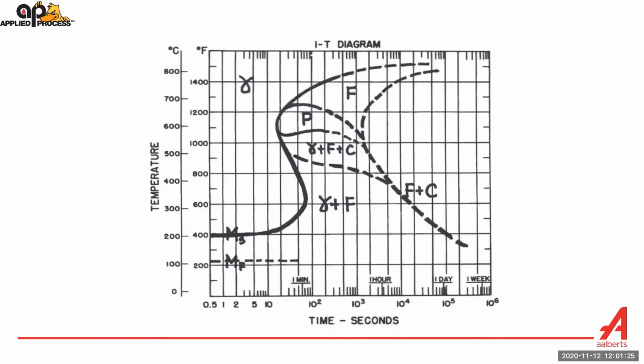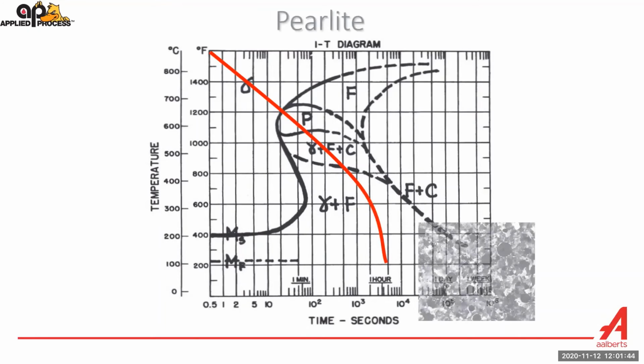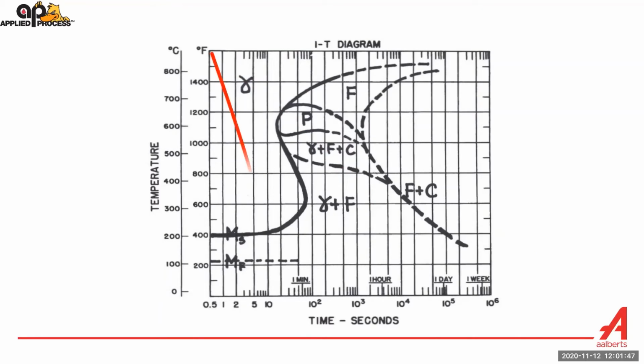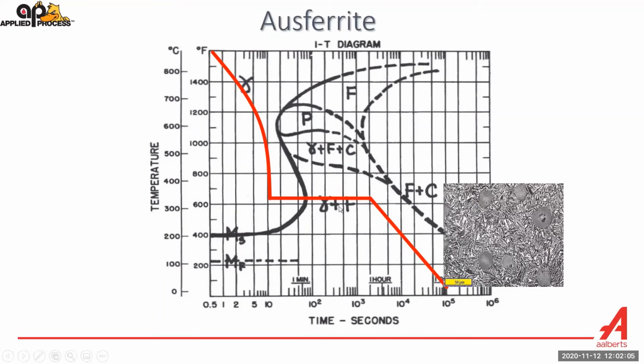So again, we go back to the IT diagram or the TTT diagram. This one is for ductile iron, though. This is a generic diagram we use to explain the process. So if you slow cool ductile iron, you get a ferritic structure. So that's annealing. If you fast cool with air, you get a pearlitic structure. If you rapidly cool using oil or water, you get a martensitic structure. And again, you have to temper it. And then there's austempering or molten salt quenching. Again, we quench at a relatively high temperature, and we hold until we produce this structure that's austenite and ferrite, or ausferrite, and there's the microstructure. So all we're doing is taking a different path through the TTT diagram to get a different, preferred crystal structure.